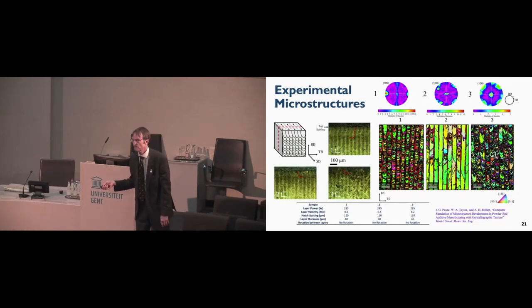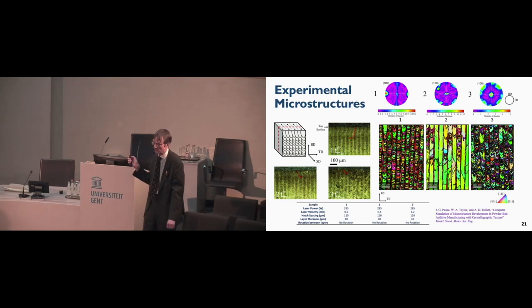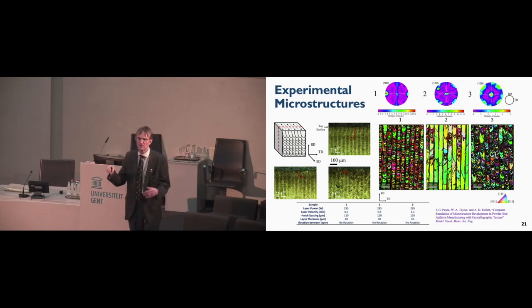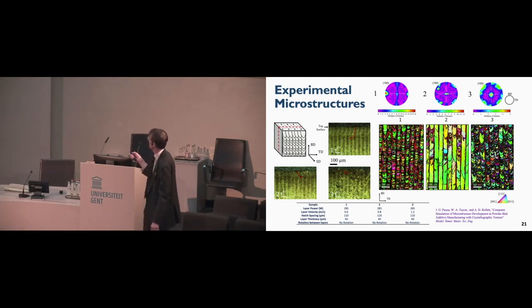Now let me try to explain where they come from. Thanks to a collaboration in Metz, we took a look at problems like this, where the scan pattern, instead of being the usual going around the clock sort of thing, was limited to just one direction. So just keep depositing all in one single direction and piling up the melt pool layers on top of each other. And so you can see the melt pool structure reasonably clearly. These were experiments with a constant power, 285 watts, and then three different speeds, if you like, slow, medium, and fast. And what you notice here is sort of an extreme version of what I just pointed out.